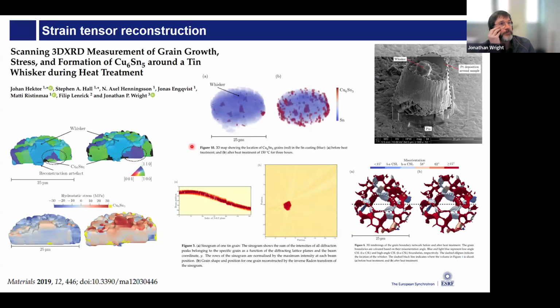So I'll try to get towards the wrap up with the strain tensor reconstruction we're doing most of, which is by these 3D XRD methods. In this case, it's the first example that I'm aware of doing on the nanofocus station at ID11, and it was a tin whisker that Johan Hektor had FIBbed out. So he found a tin whisker starting to grow. It's a piece of copper with a thin layer of tin on the surface. And these whiskers grow and cause all kinds of problems, and they wanted to understand what was happening there.